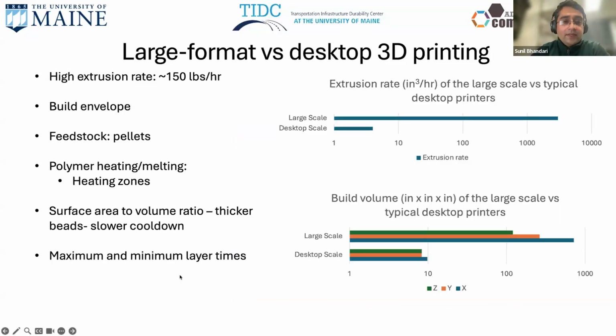Many of us might be familiar with desktop 3D printing, which uses filaments that come in desktop sizes. But large format additive manufacturing has very high extrusion rates. The machine we saw earlier had a maximum extrusion rate of 150 pounds per hour, and since that video, we have made some modifications, and now it can do up to 400 pounds per hour. And there's a newer one being made that can do up to 1,000 pounds per hour.